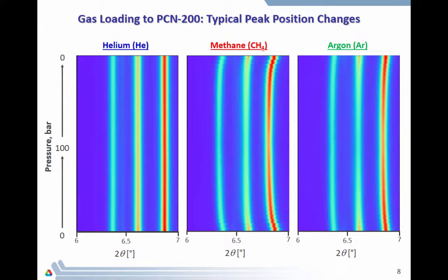And okay, so we can set up the system, and the users immediately would see from the top view plots how the material actually reacts to different gases under pressure. How we can show in this example is that with helium, the MOF didn't have any effect on its structure, while when we use methane and argon, we can clearly see the powder pattern peaks moving with the pressure and returning back while we release the pressure, and therefore we can see the effects of the gas pressure on the MOF itself.